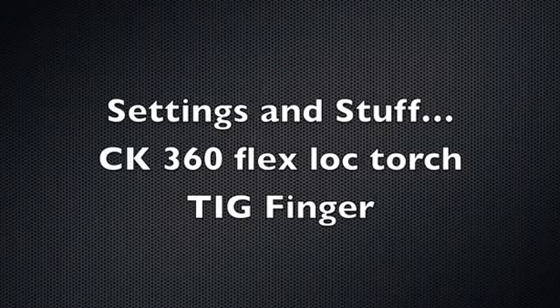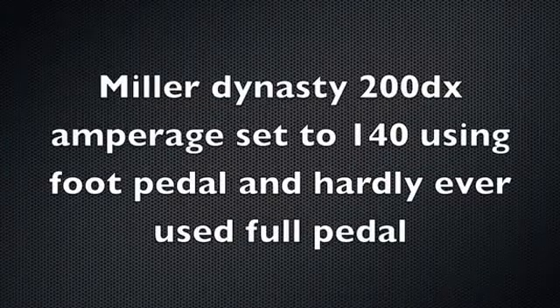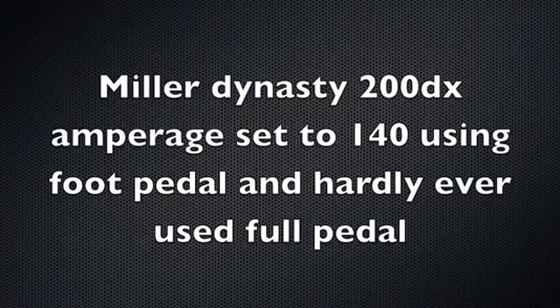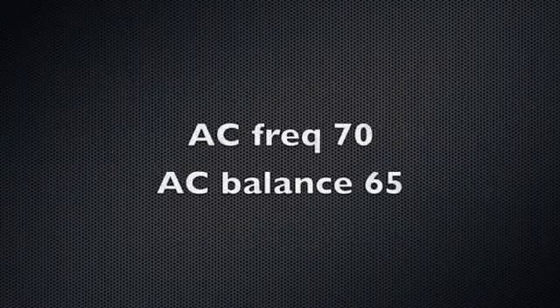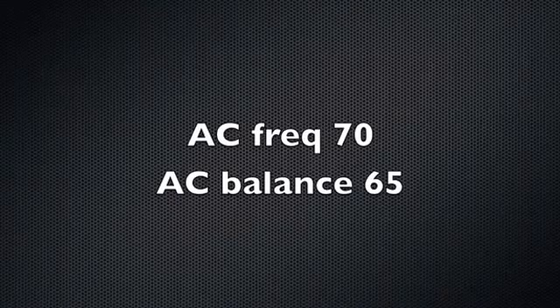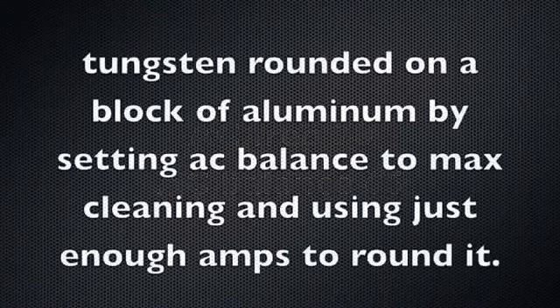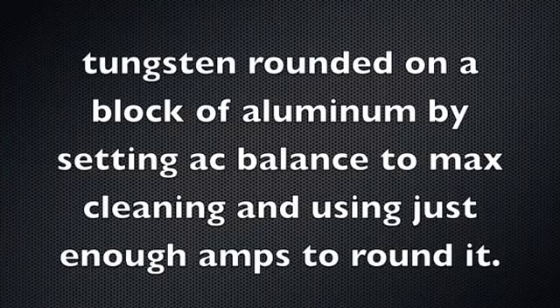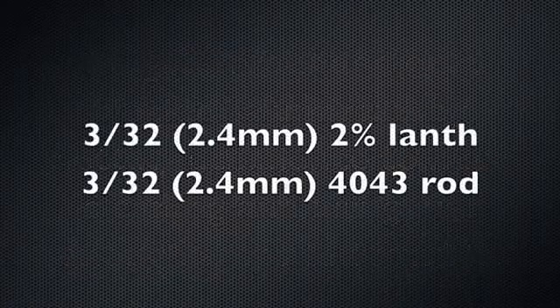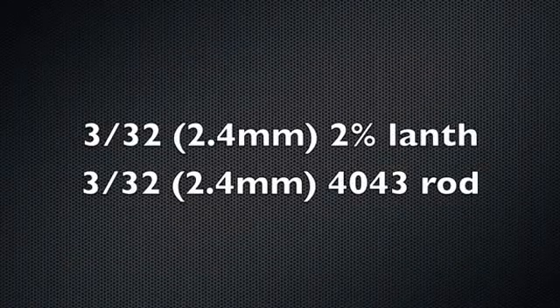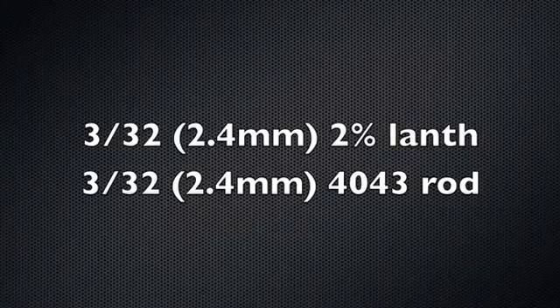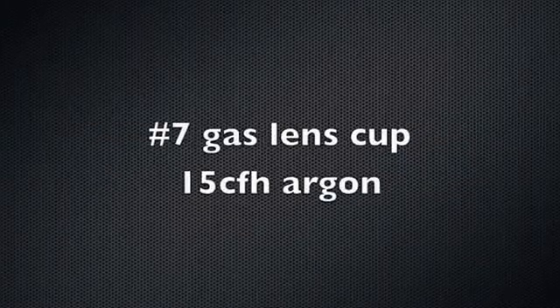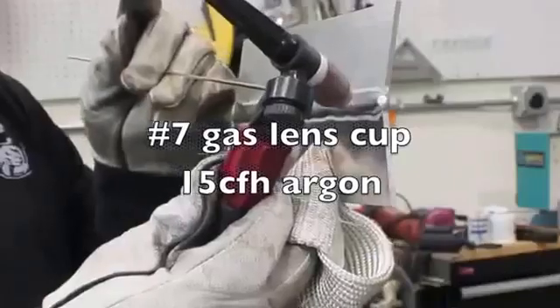So settings and stuff, I use a CK360 flex loc torch and a TIG finger. I use a Miller Dynasty 200 DX, amperage set to about 140, but using the foot pedal, and hardly ever got to even full pedal, just when I was starting out beads. AC frequency on 70, AC balance 65. Tungsten rounded on a block of aluminum by setting the AC balance to the max cleaning and using just enough amps to round the tip. 3/32, 2% lanthanated electrode, 3/32 4043 filler rod, number 7 gas lens cup, and 15 CFH of flow on the argon.